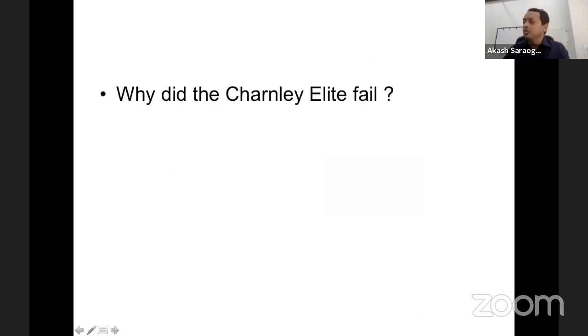Okay. So one more question that can be asked is about the past failures of the implant. So they can ask you why did the Charnley Elite stem fail? There was a study which was done, which was a radiostereometric study, published in 2003 in JBJS, which suggested that the Charnley Elite failed because of high posterior head migration. So in the plastic, the head would migrate posteriorly, and that is why the Charnley Elite stem failed. There are reasons why we did go into that, but let's not get into it because it will save us some time.